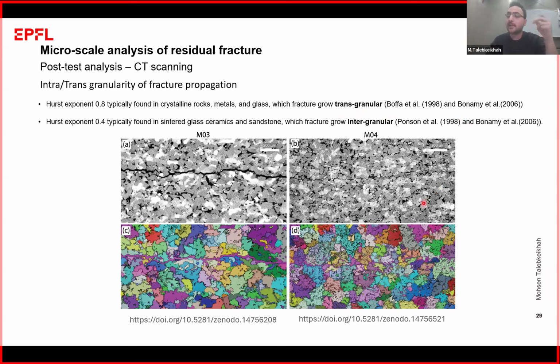To check that, we did another CT scan with higher resolution to better detect the fracture path and also the particles. We could see that the fracture really goes through the porosities and is not breaking any particles. Here in the bottom figure, we can see that the Avizo software detects the particles by segmentation, and none of the particles are broken. The point is that we asked for a thin section analysis, but up to now I don't have the result to show. I think I can have it in the next two weeks.